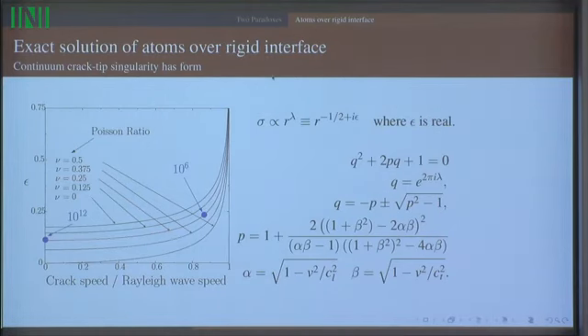What I've done here, I have a gob of undigestible details about the continuum solution, but I just want to emphasize that there do exist closed solutions that will tell you what this exponent is in terms of the wave speeds in the upper solid, which is the only thing I'm allowing not to be infinitely stiff, and also in terms of the speed. If it's a moving crack, then there are corrections to the exponents, and I computed all of those too. And what I indicated here with these blue numbers, 10 to the 12 and 10 to the 6, is an estimate of how many